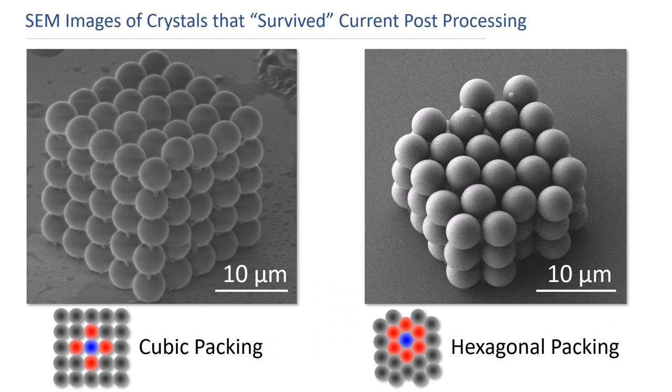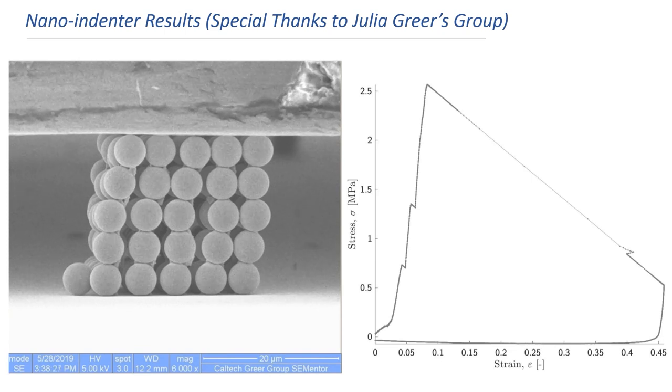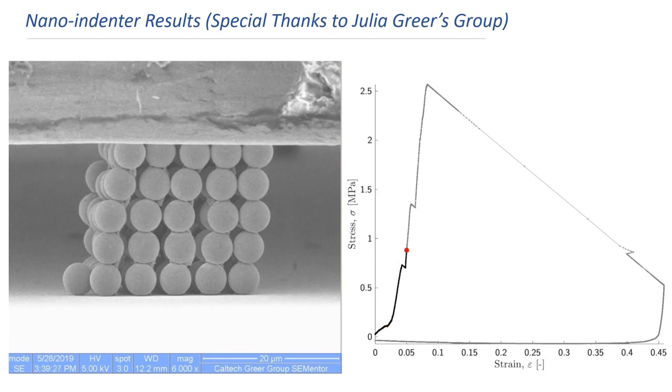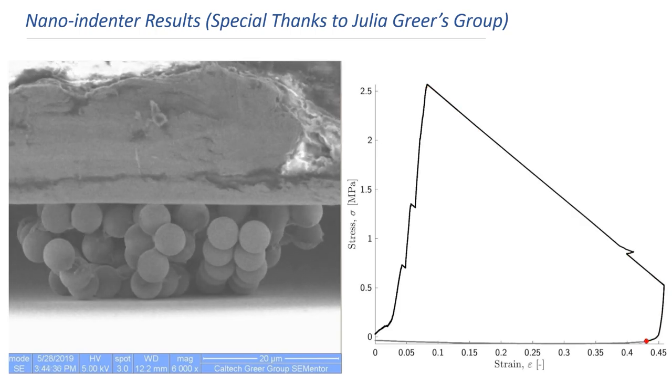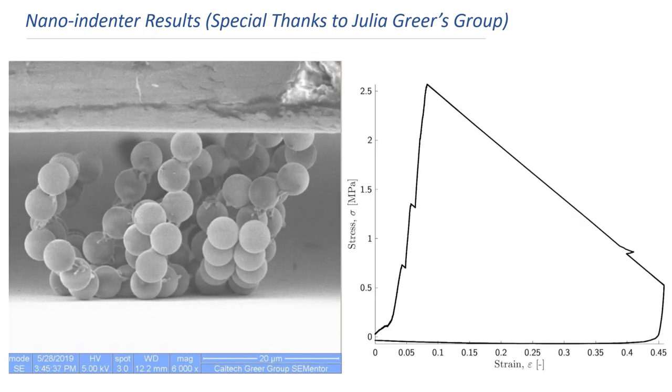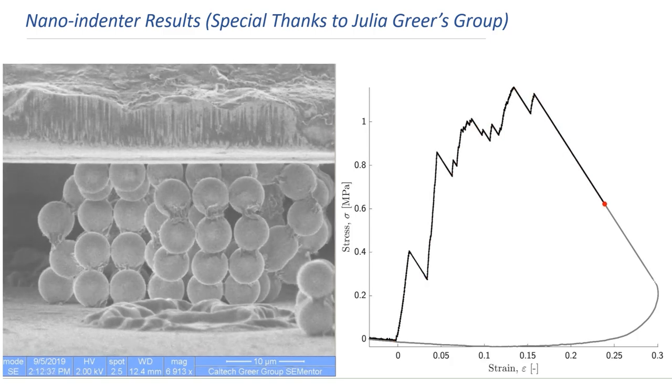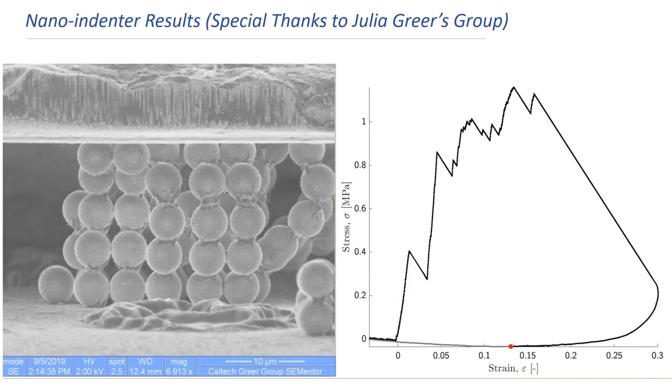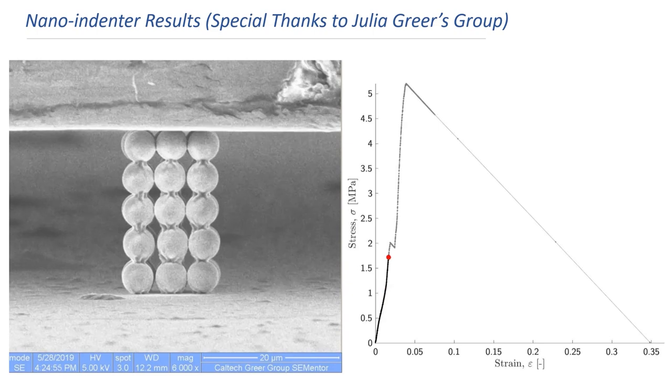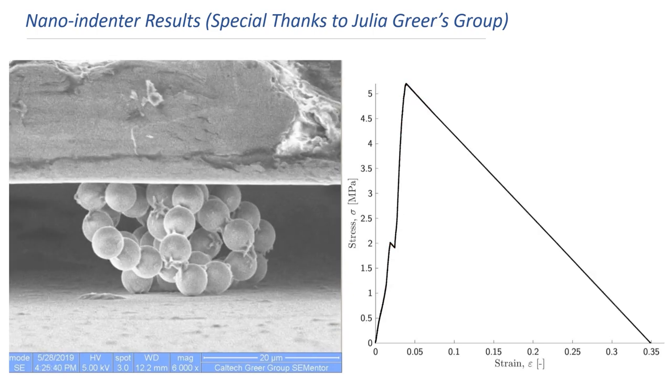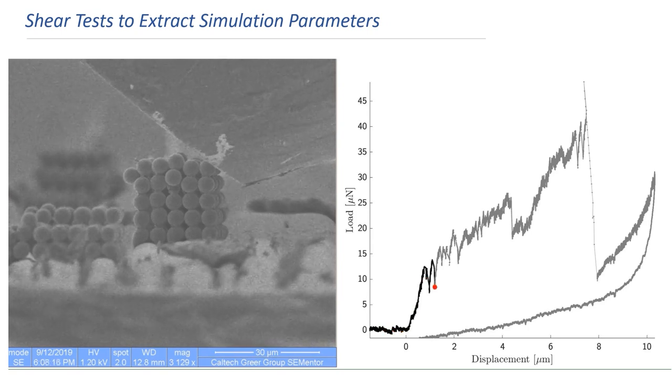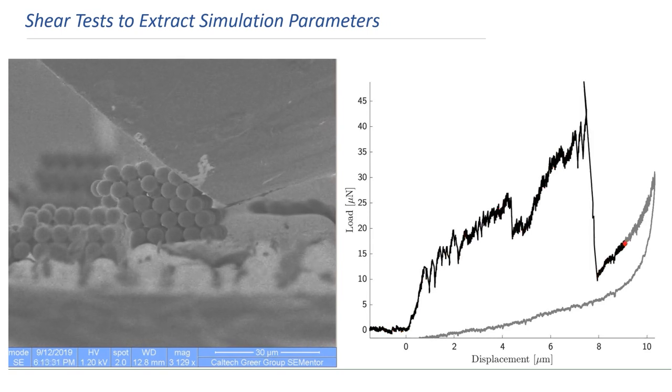You'll notice from these crystals that we are not restricted to making cubically packed lattices but can also assemble hexagonally packed lattices and really any other desired crystal lattice configuration desired including graded designs. Carlos Portela helped us collect mechanical testing data in Julia Greer's lab on our initial crystal samples. The sudden fluctuations in the rising stress at the beginning correspond to columns of spheres buckling along the crystal's outermost walls. We expect better data when we test future more orderly samples. You can clearly see, however, the X-shaped glue joints directly below each sphere as they are torn during testing. We also conducted shearing tests on some of the crystals to characterize the stiffness of the lateral bonds between the spheres as well.